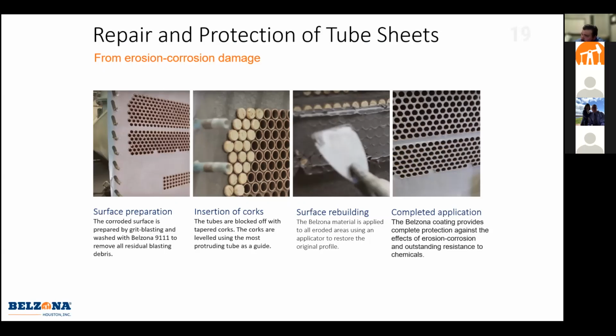You can see in that third picture from your right, we'll use that as kind of our guide. And especially on your roller expanded tubes that stick out 1/8 of an inch to 1/4 of an inch, that's giving you even more Belzona material to erode away for you in place of your metal. So all the way on the right, you can see our completed application with our 2-coat system of our ceramic epoxy. That's after we pop the corks out and hone the tubes back for you. Looks better than new.